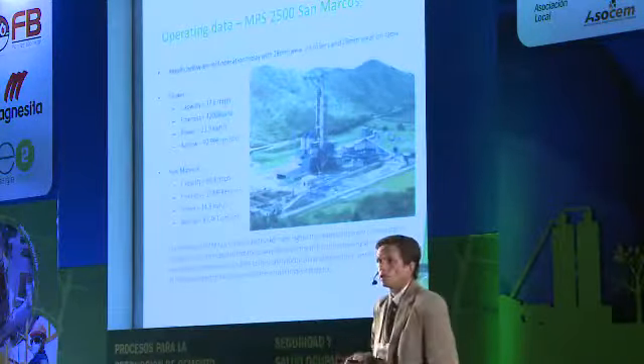So here you can see the operating of the mill, some operating data. These are some results that were taken after the mill is already somewhat worn. We have 28 millimeters wear on the roller tires and approximately 19 to 20 millimeters wear on the table. The mill in clinker is grinding at 37.6 tons per hour and a fineness of 4200 Blaine. Of course, the power consumption, 23.9, and if you have a look, the airflow at 92,000 normal cubic meters per hour.